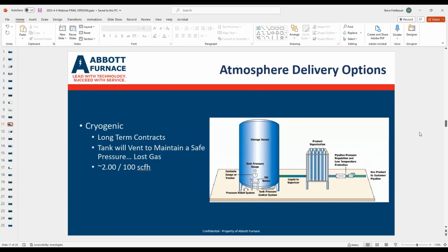Now, this is a little conservative. The prices that I was given recently were right around $1.50 per 100. But so that we were safe and on the conservative side, we've used the value of $2 per 100 standard cubic feet of gas for the calculations. And we use this for both the vacuum calculations as well as the continuous furnace calculations.